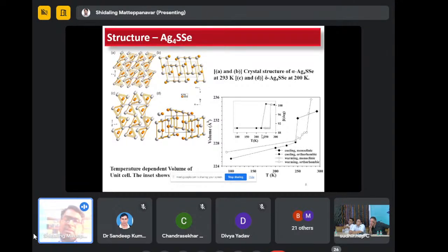But we are not interested in the high temperature part; we are interested to see the charge density wave in this sample. So that's why we have studied the low temperature X-ray studies, basically synchrotron X-ray studies or high energy X-ray studies. And we saw a surprising result: this compound shows a very sharp transition around 250 Kelvin, from monoclinic to orthorhombic structure.